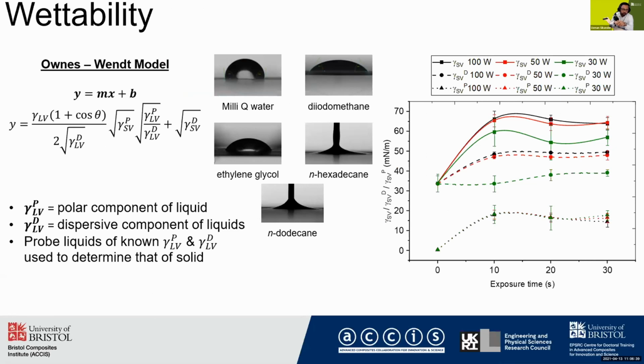To understand how the plasma treatment enhances the wettability of these fibers, we used Owens-Wendt model to understand the wettability, which essentially uses two different liquids, such as one with the polar component and one with the dispersive component. And then you find the contact angle of the drop that is being placed onto the surface.